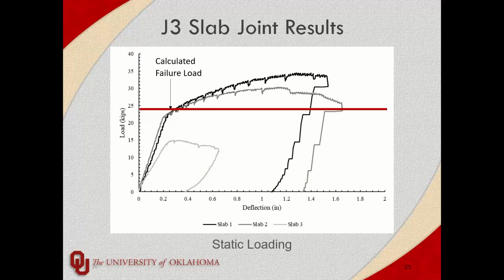And in this one, this is for J3. You'll notice we didn't get quite as good ductility as we had, but we did still exceed the monolithic slab strength, which in my opinion was the most important. And the overall failure loads were slightly lower. But even with the fatigue test, the cyclic loaded test, we did have a lot of ductility in that, just like Ductal did, which I thought was great.